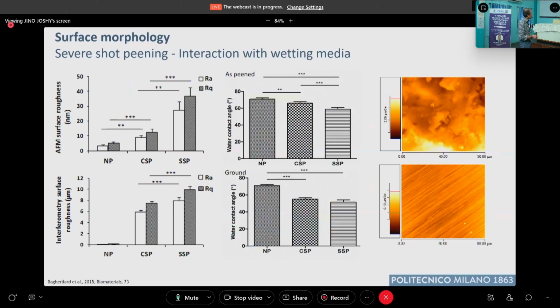This is the roughness measured with an atomic force microscope. We consider the non-peened sample as reference, the conventionally shot peened sample, and then severe shot peening, and this is a confirmation of the higher effect of severe shot peening in terms of roughness. Here is again roughness, but measured with the other method, interferometer surface roughness, and again the same comment can be made.